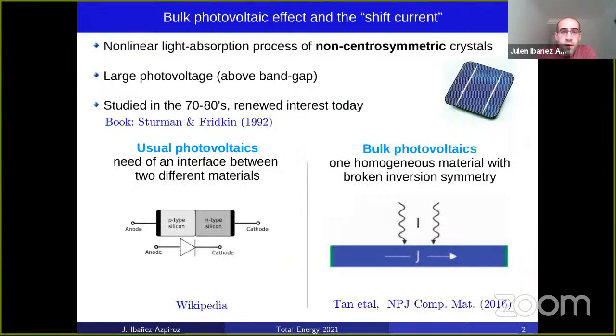So today I will talk about the shift current, which is an effect that is a particular contribution to the bulk photovoltaic effect, which is a more general effect, although often both terms are used interchangeably. Now, this consists of a nonlinear light absorption process that takes place in non-centrosymmetric crystals. That is, the material must break inversion symmetry in order to show this effect. Very large photovoltages above the band gap value can be attained in this effect, and it was largely studied during the 70s and 80s, but we find renewed interest today.